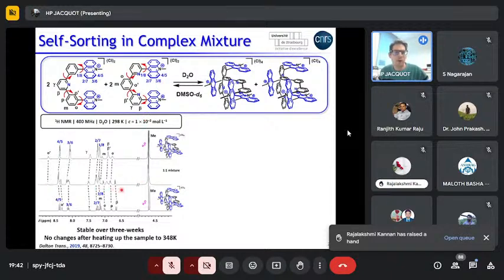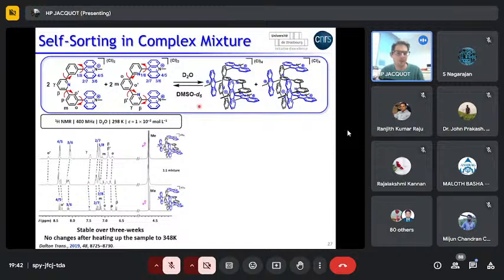And you have the corresponding proton NMR spectrum in D2O. What you see is that you have only two chemical species in D2O, which correspond to the homodimers. So when you mix tweezer A and tweezer B, you end up with dimer AA and dimer BB with no formation of AB. This is what we call a narcissistic self-sorting process. Then this solution, the one-to-one mixture, is stable over three weeks on the benchtop. And you can also heat it up and nothing happens.